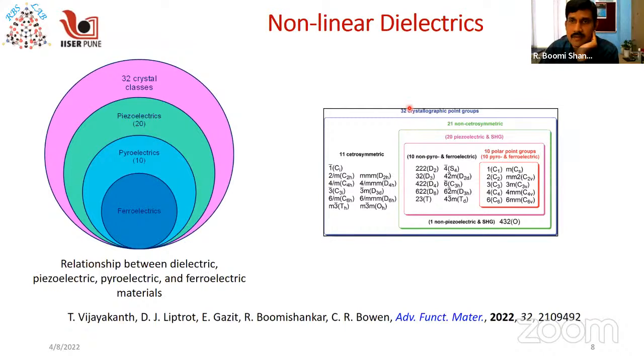Okay, so there are about 10 or 11 of the 32 crystallographic point groups that are centrosymmetric. Because of that, the dipole moment in the system gets cancelled across the inversion center or the mirror plane. Therefore these materials will not have a permanent dipole moment in the system, and will not show any nonlinear dielectric properties. Okay, so of the remaining 21 non-centrosymmetric systems, one has the highest symmetry. As a result, the dipole moment in the system gets cancelled even in that particular point group, which is called the 432 point group. Then what is left over is again 20 point groups. Now all the 20 point group materials can exhibit piezoelectric properties. However, only 10 of them will have a unique polar axis, which will exhibit pyro and ferroelectric properties.